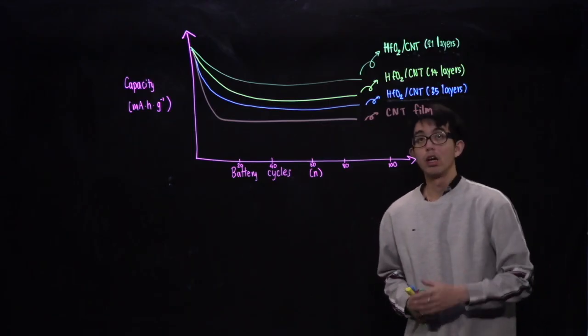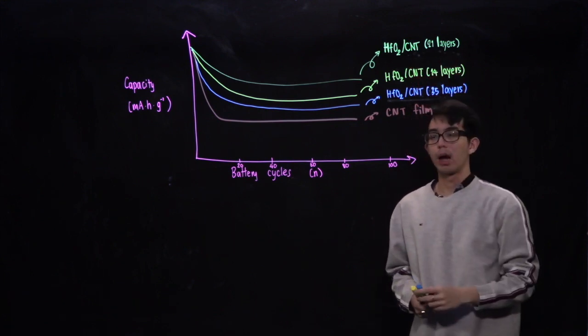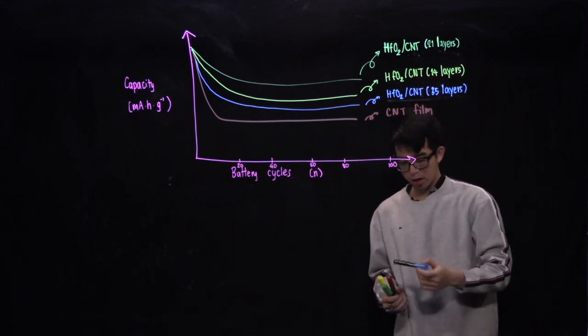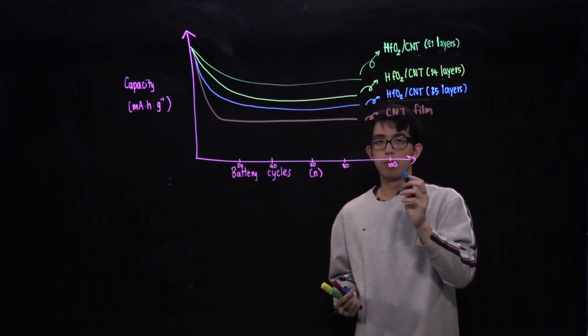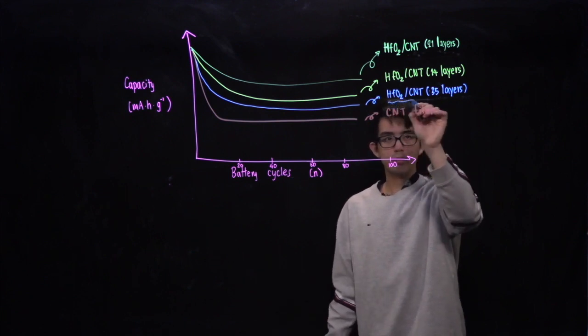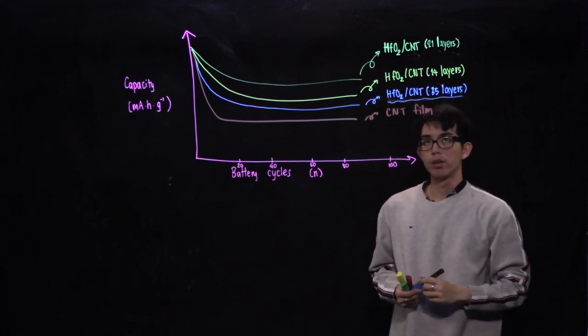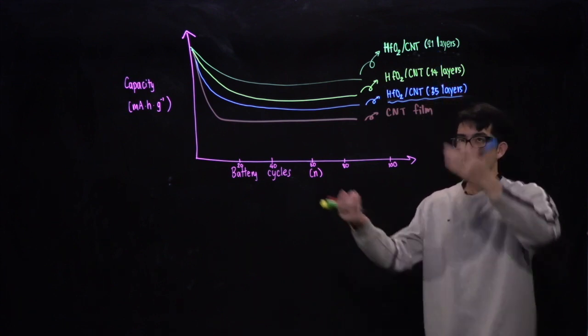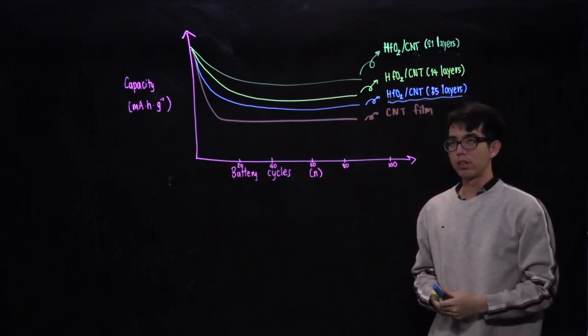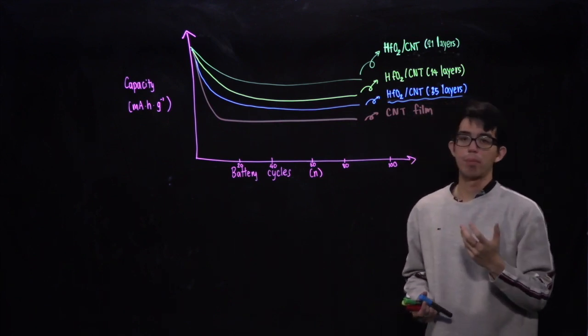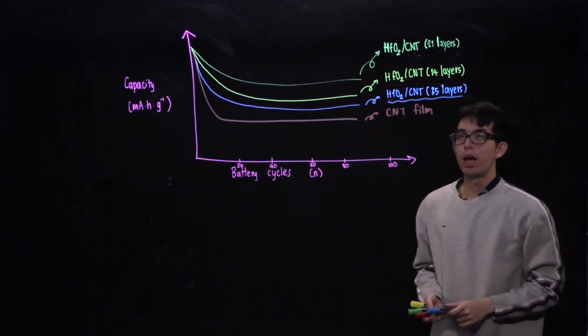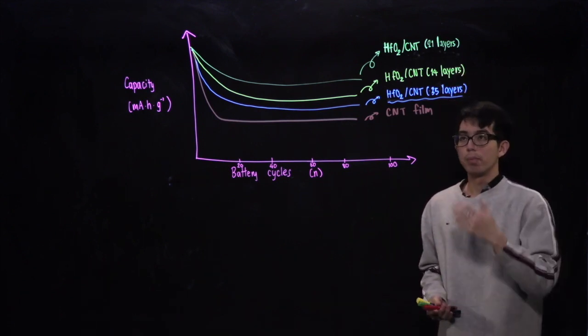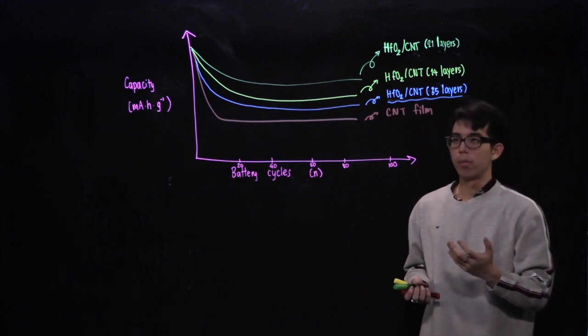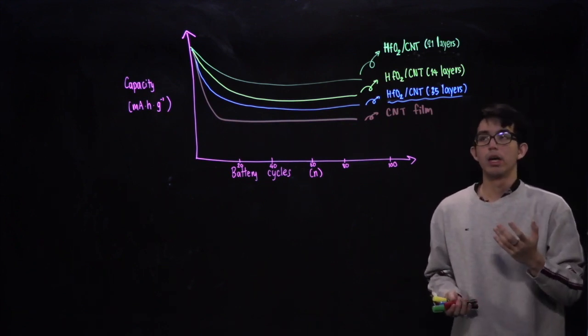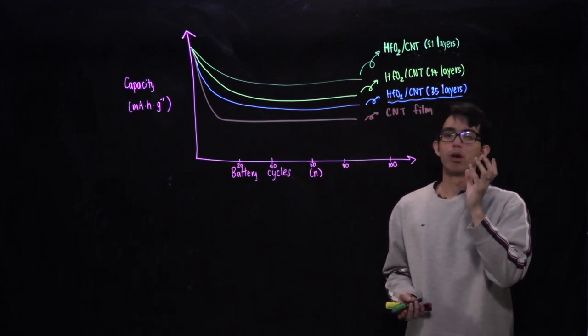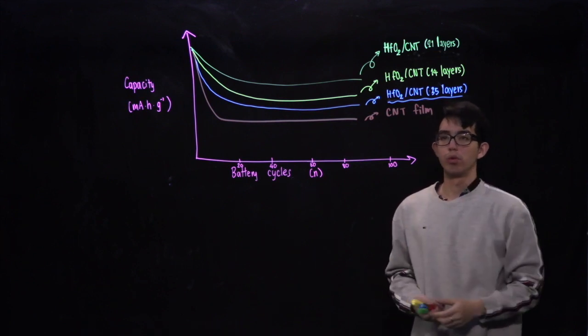However, having too thick a layer of the hafnium oxide carbon nanotube might not be a good idea either, because it might interfere with the charge transfer between anode and cathode. Like in this case, having 35 layers performs worse than having 21 or 14 layers. However, as you can see, having 14 layers is not efficient either, because it may not be able to trap polysulfide that well. So at the optimum level, 21 layers seems to be perfect, because it balances both the polysulfide trapping effect and the availability to allow lithium to cross through the separators.